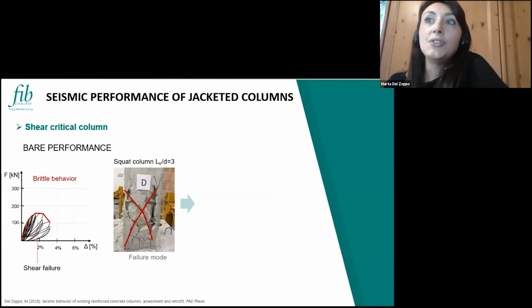Then the second application is about shear critical columns. In this case, we have another specimen that exhibited a very brittle behavior during the cyclic test with a poor ductility performance and without achieving, of course, the yielding of the rebars. And these are the classical diagonal cracks developed on the specimen due to the shear.